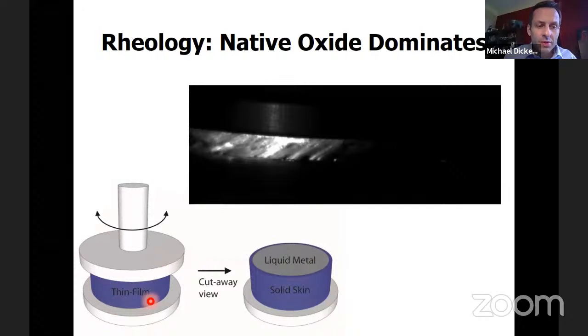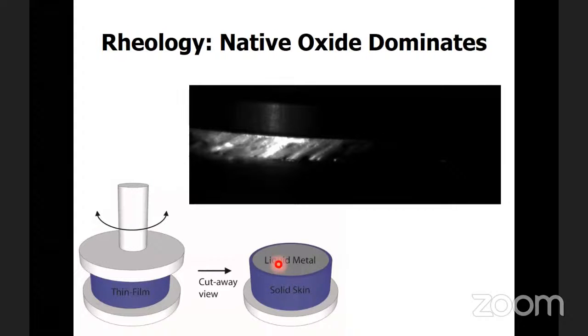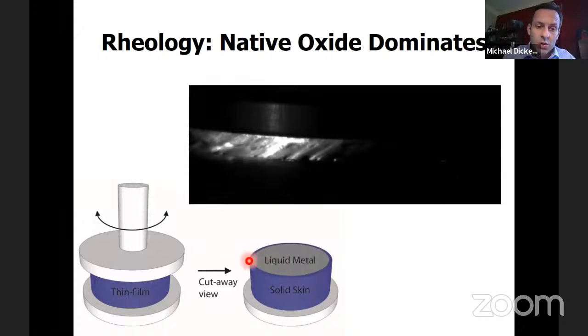And so what we did is we put the liquid metal between two plates, and we turn the plate back and forth. This plate is about the size of a cookie, so it's about this big. And what we measure is the torque required to turn this back and forth. Now, normally this is a bulk measurement, which means we're measuring the entire material. But if you take a cutaway view, the liquid itself is like water. So it's got a viscosity, but it's so low that you really can't measure it using this technique. So what you're really measuring is this solid skin.